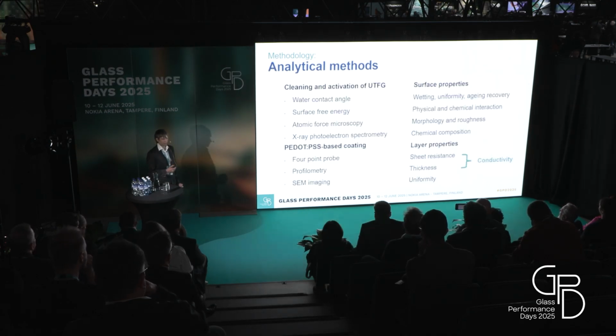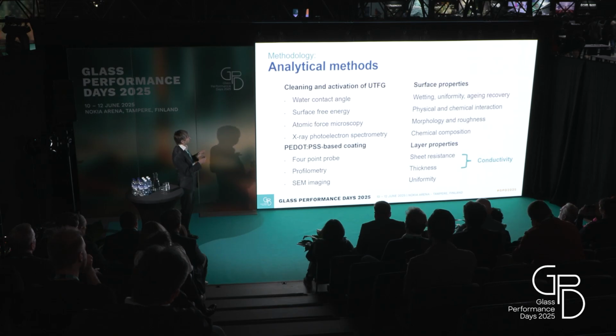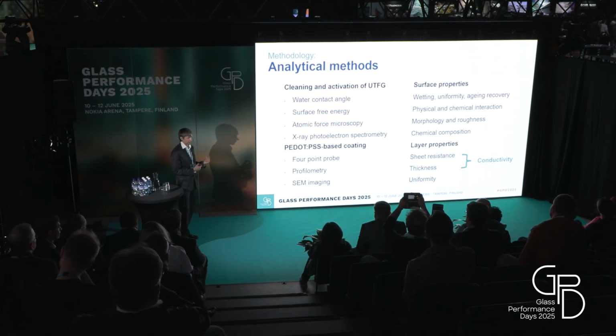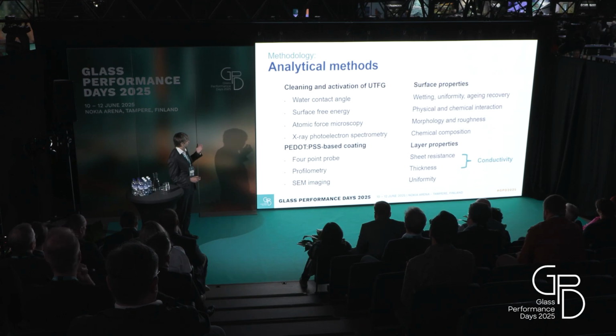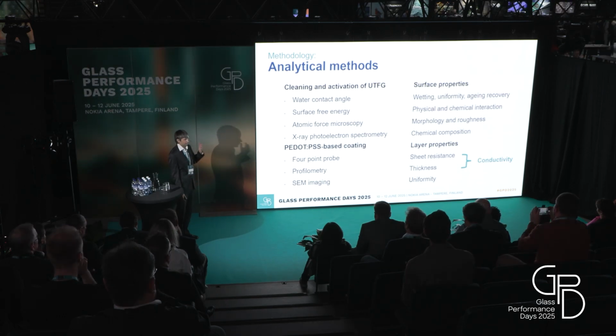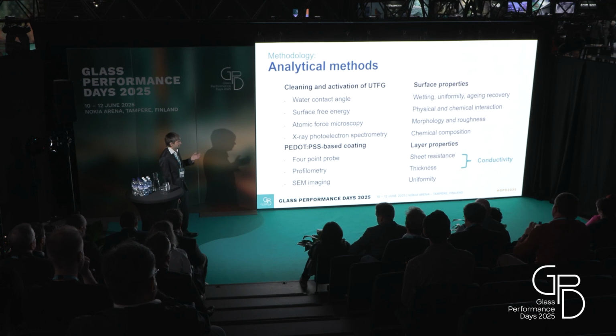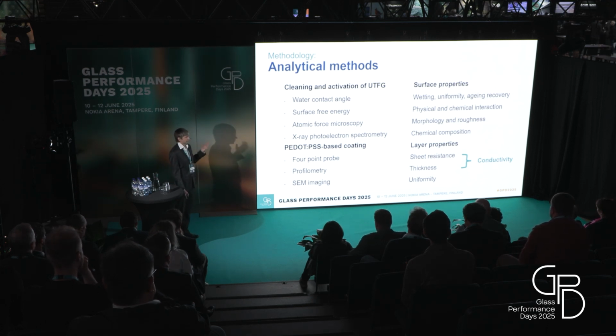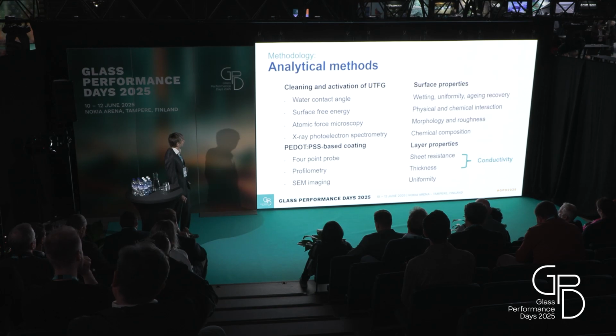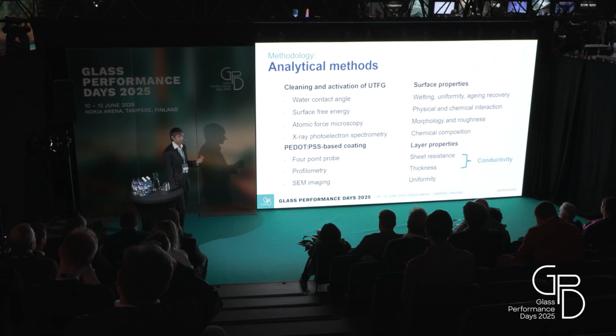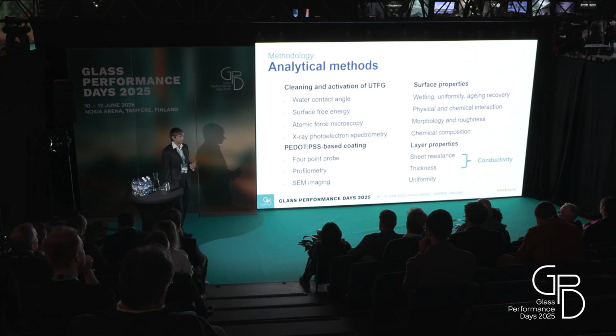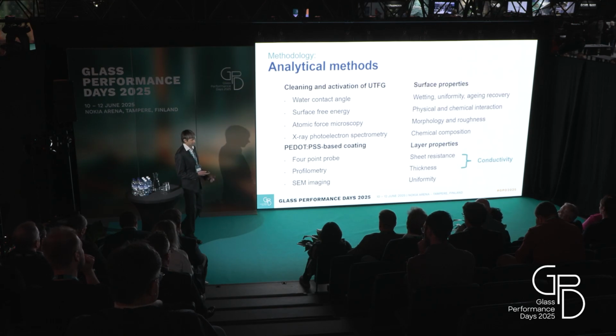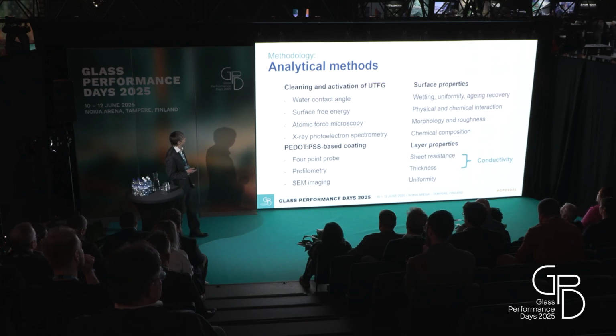So how did I analyze my experiments? First, I analyzed the plasma-treated ultra-thin flexible glass. We used methods for evaluating if it's activated, if the morphology was affected by plasma treatment, and tried to find out what is behind the effect, so chemical changes. And then afterwards, I made the coatings, and I tried to evaluate their qualities for transparent conductive electrodes, so I needed to evaluate sheet resistance or conductivity for thickness, and also I was observing if the samples are uniform, because this is key for their performance.